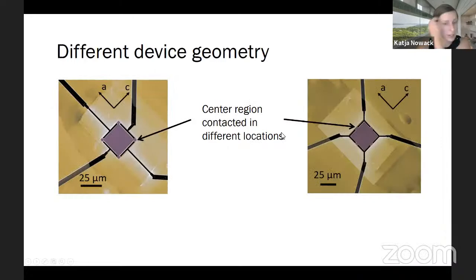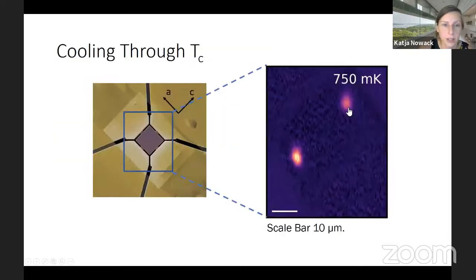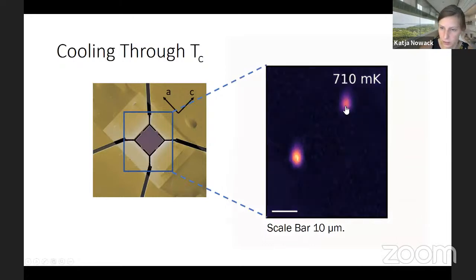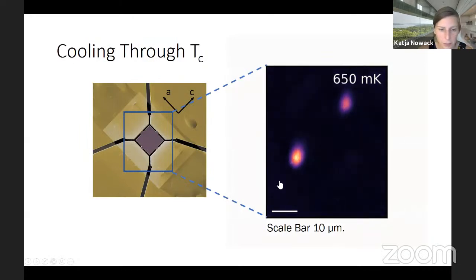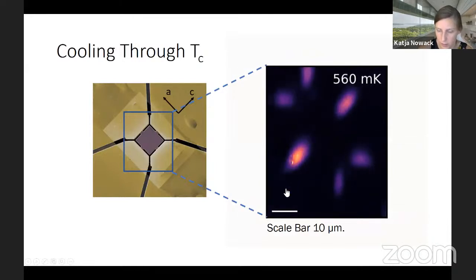Let's look at a second device. At face value, this looks very similar. It's also a square, with the only difference that now the electrical contacts are in the middle of the sides. Let's also look at a movie of this one, how it goes through TC. And so here now it's playing. We start with little superconducting speckles that are located in these little bridges right here. And if we go to lower and lower temperature, now slowly we see something happening. There's something coming up here. These regions get a bit more elongated.